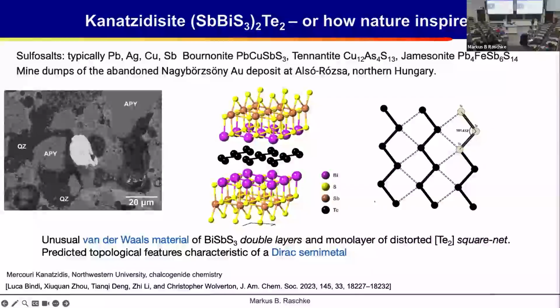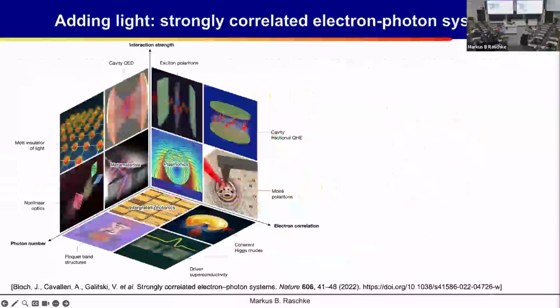And here's a very recent mineral described in 2023, which is what's called a sulfosalt. It has sulfur and tellurium, and then there's antimony and bismuth. And it turns out that this forms these sheets, these tellurium sheets, which have this zigzag pattern. And it actually turns out that such a sheet of this distorted square net would suggest to be a good candidate for what's called the Dirac semi-metal. This is a material which is similar then to graphene, and that would be a potential candidate for new materials.